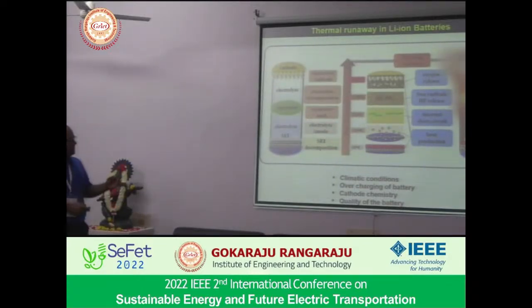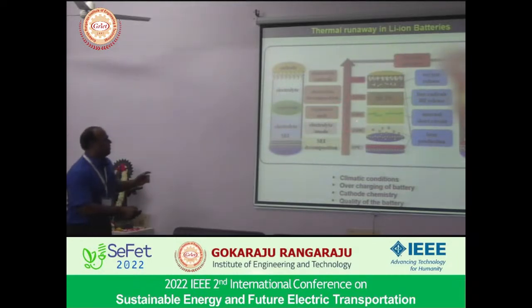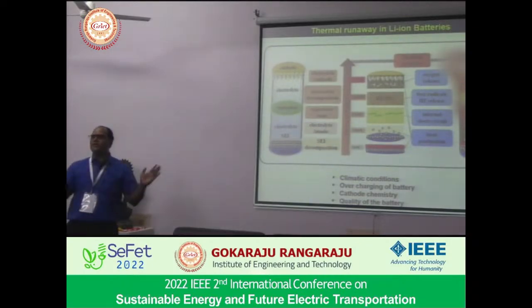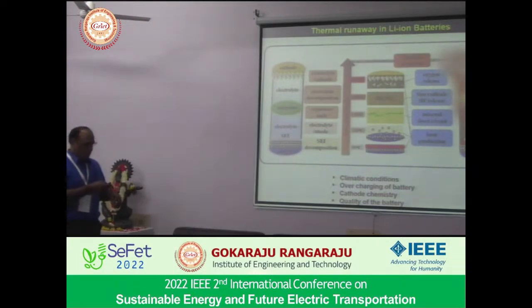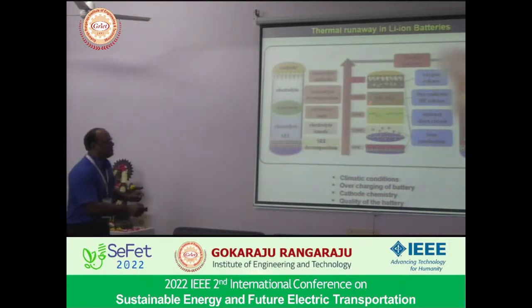And then once that started decomposing, the temperature slowly increases, and the separator, as I mentioned, is only 20 micron thickness. It cannot withstand this high temperature, and then the cathode and anode will be shorted. Once this short happens, the temperature goes to 200 degrees centigrade, and then HF, a strong acid, will be generated, because in your electrolyte you have LiPF6, that fluorine is there.